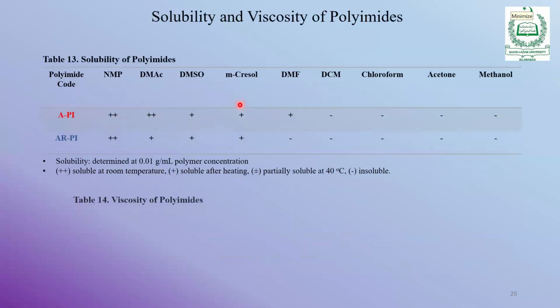Solubility and viscosity. If you have a polymer and you want to coat it, the polymer should be soluble in some solvent. The solubility data shows that in DCM, chloroform, acetone, methanol, they are not soluble. This is the usual characteristic of polymers. Then in DMF, they are soluble after heating. Same with metacresol and DMSO. And the first one is soluble at room temperature in DMAc and NMP, while the second one is soluble in NMP at room temperature. So this window is the working window for us to play with this polymer. So for coating we can use these two solvents.